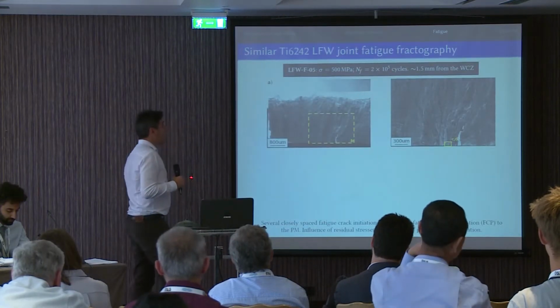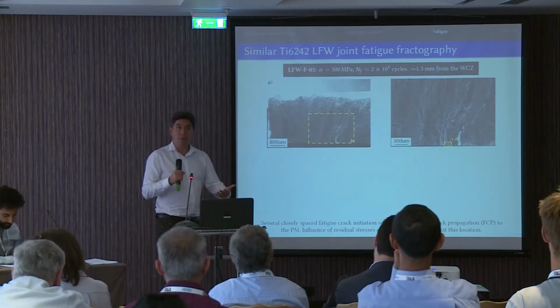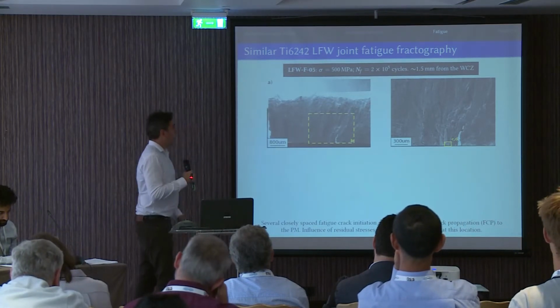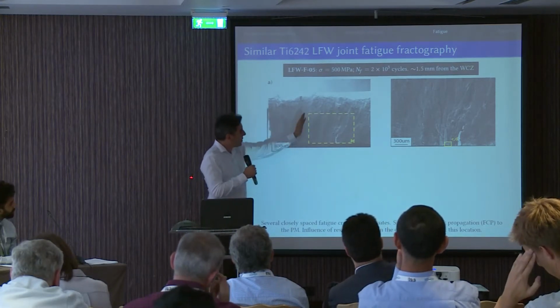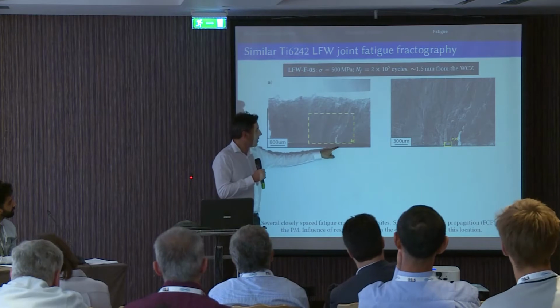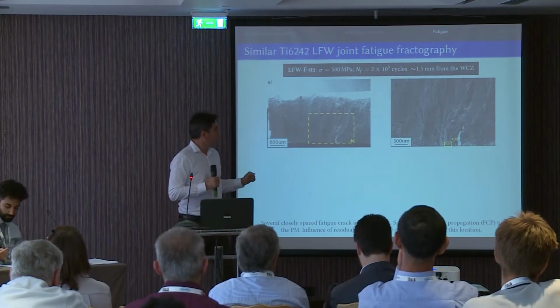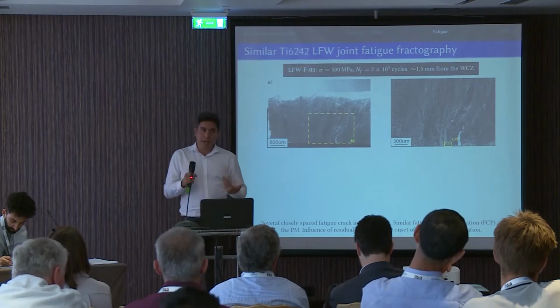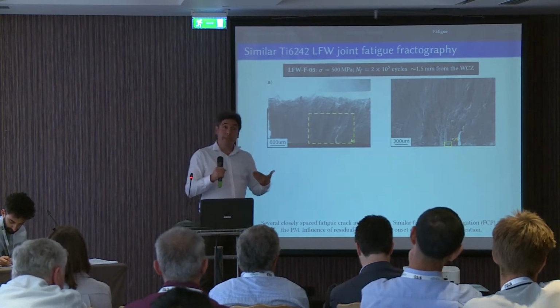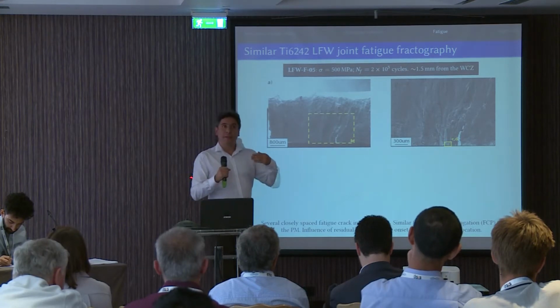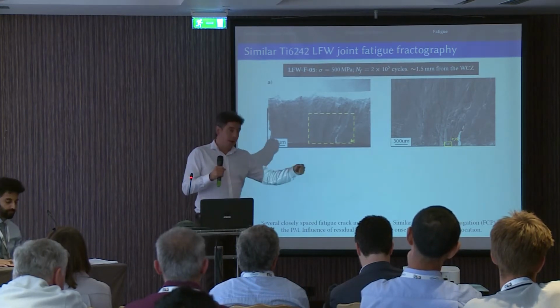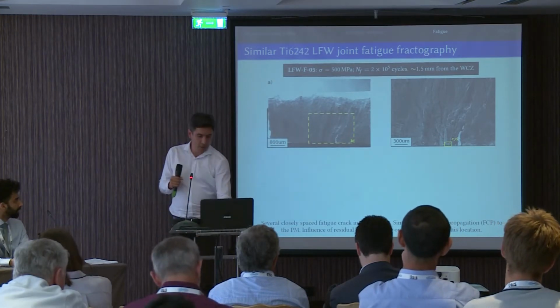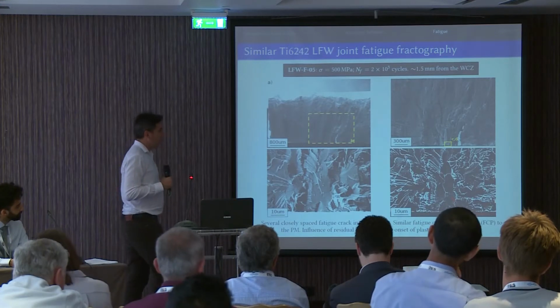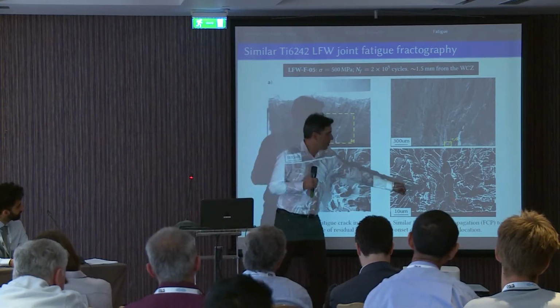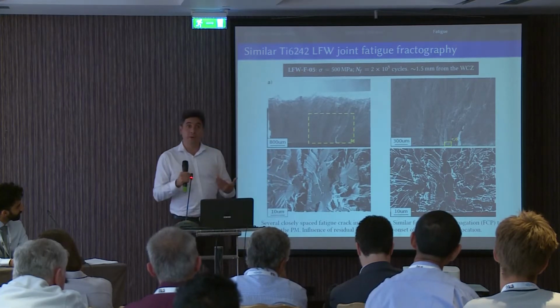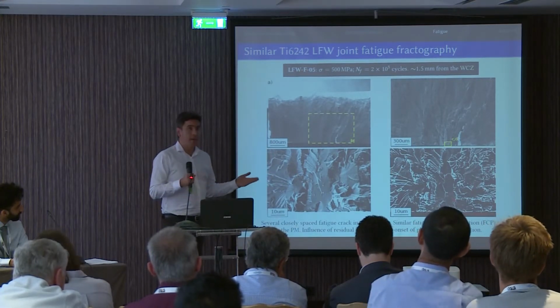So we'll study the fatigue crack mechanism for the first specimen, the one with the long life, the one that broke far away from the weld. And what we can see are fatigue ridges that converge to several points on the surface of the specimen. We can see it here also. This could be explained by the residual stresses we mentioned. So maybe the stress was enough to activate several crack initiation sites at the same location. And if we look closer, we can recognize here features that convey the shape of the alpha grains. So we observe stage 1